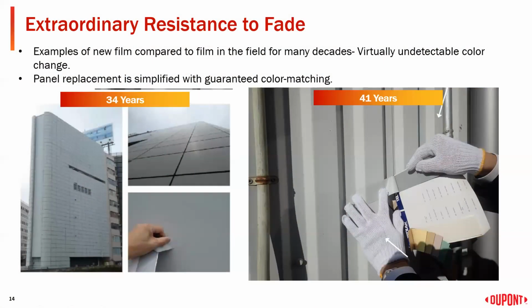So what you're seeing here is a real world example of that resistance to fade. So we have two facades. One has been out for 34 years, one for 41 years. And what you're seeing is us actually holding fresh film, freshly manufactured film, right up against those aged facades. And you can see the film that we're holding up is exactly the same color as the side of the building. So there has been no visible color change in those 34 and 41 years of outdoor exposure. You know, when you look at that on the left, you can't even hardly see it. You can't even see it. It just goes right in. Yeah, exactly. That's amazing. We have tons of examples like this. So we know that Tedlar is going to look really good for a long time.